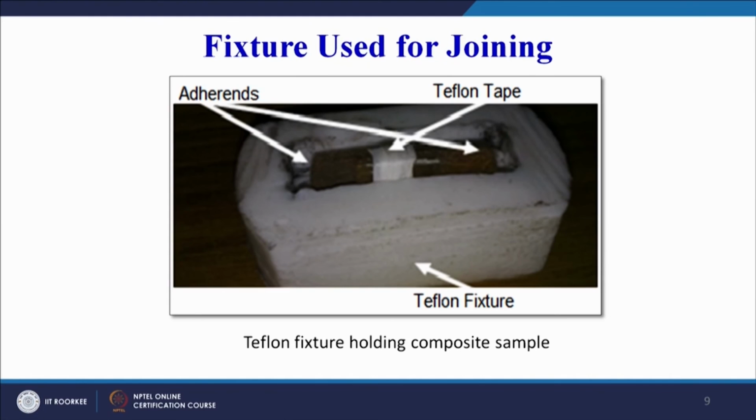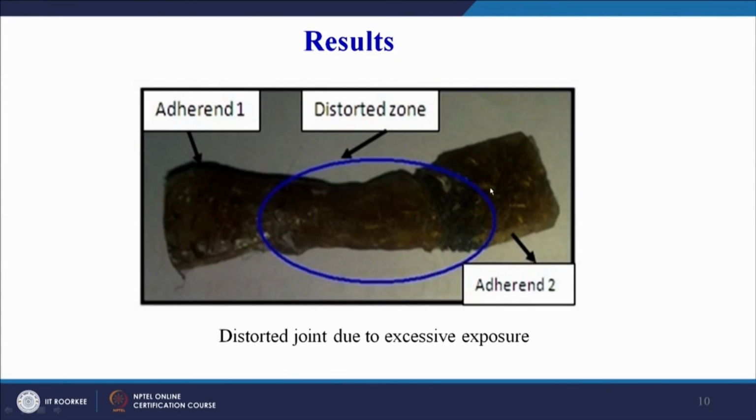Now what is ideally required is that these two parts must join successfully, but that is not possible easily because of the number of iterations, number of combinations of power and time that we have to see, and even sometimes we have to establish where we must keep our assembly, because within the microwave also there is interference of the microwaves happening and there are chances of the development of hot spots inside the material that we are keeping.